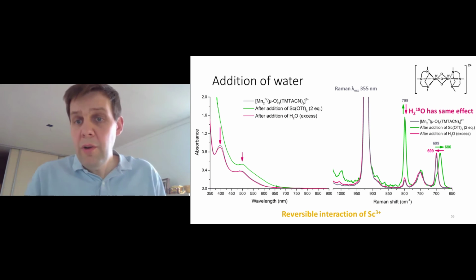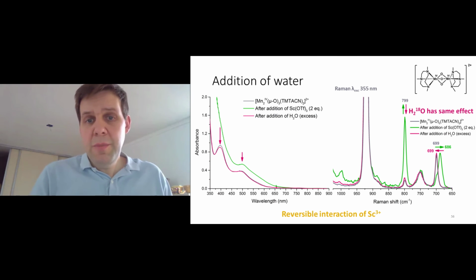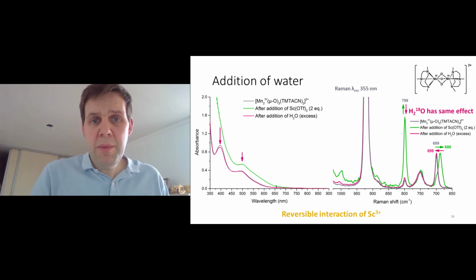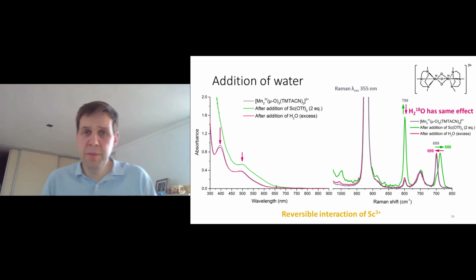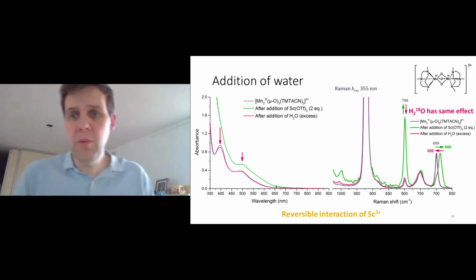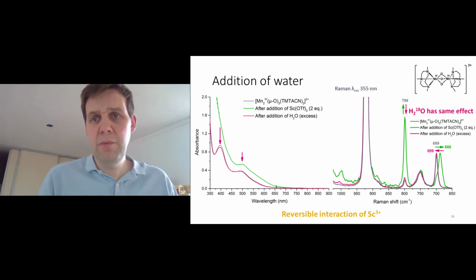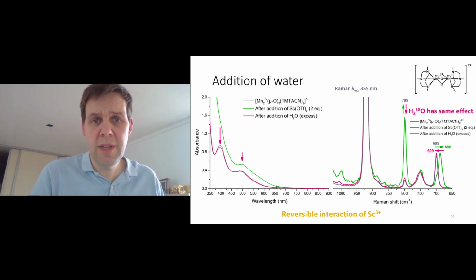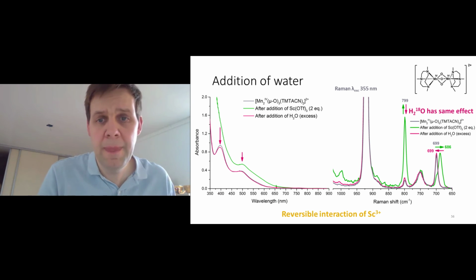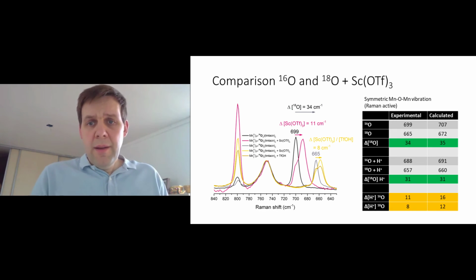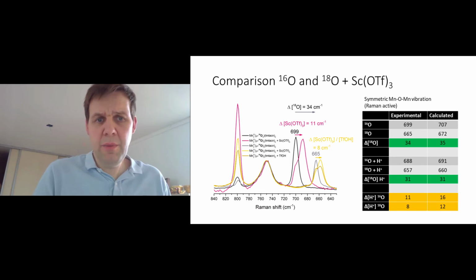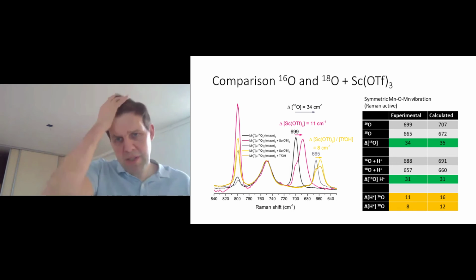If we add water or add O18 water, everything goes back to the original thing. So we reset. And remember, when you add hydrogen peroxide, you're adding a 50% solution of water. So there's always a lot of water added, an excess of water. So once the hydrogen peroxide is added, the complex goes back to its original state. So the scandium has actually done nothing permanently. We calculated the shifts we expect with scandium, and they didn't match what we got. And that raised a question, what is the scandium doing?